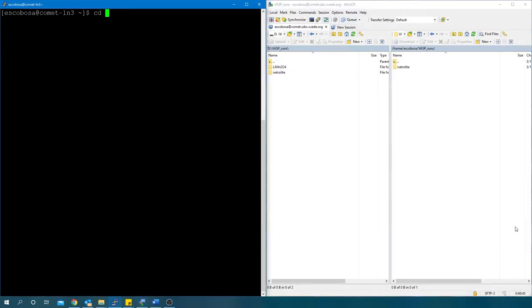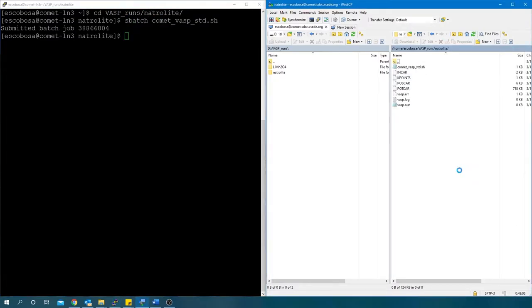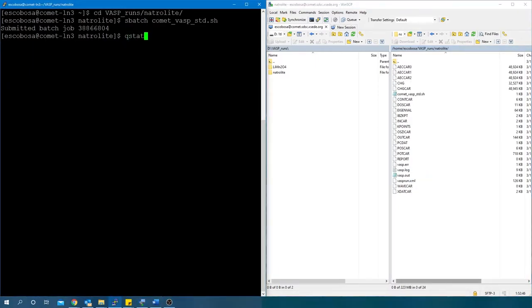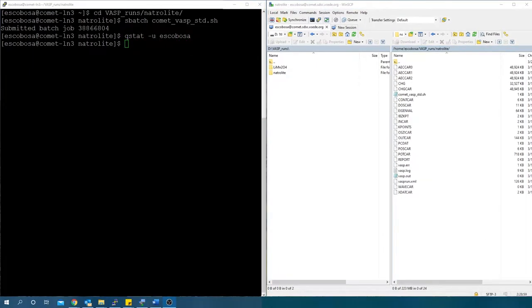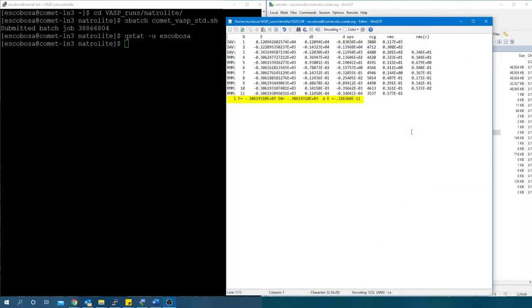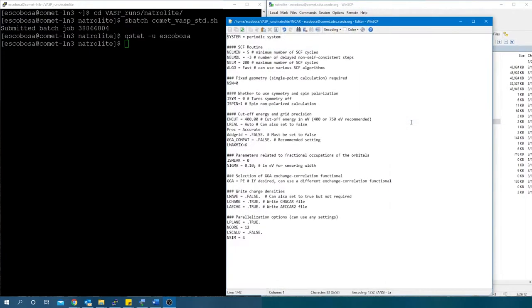Run the job and refresh from time to time. Check the status of the job and when complete, open the OUTCAR file. When running a fixed geometry, you should only have one geometry to get the total energy. And it converged if the total electronic steps N were less than the specified in the INCAR file for NELM. In this case, it converged in 11 and 200 was the maximum.